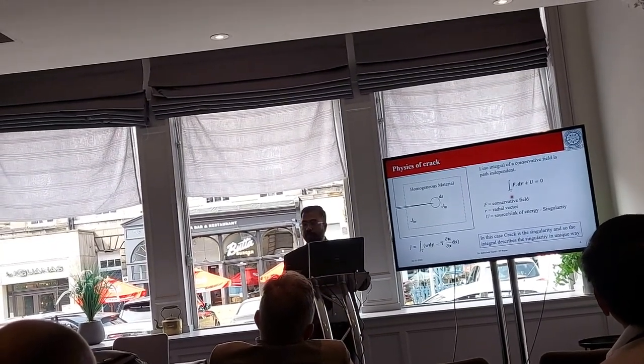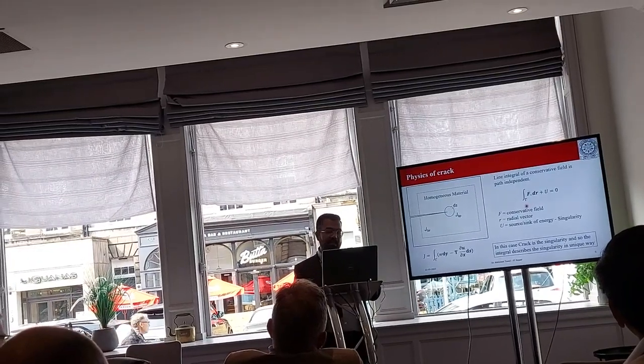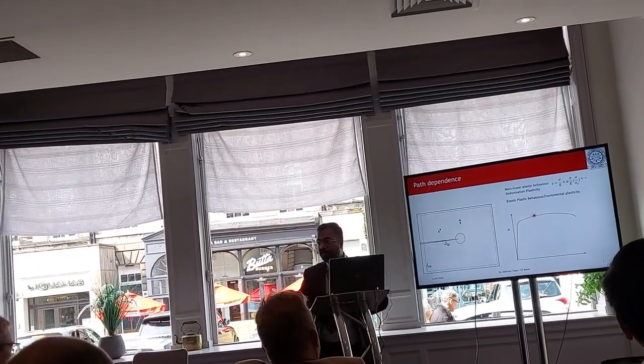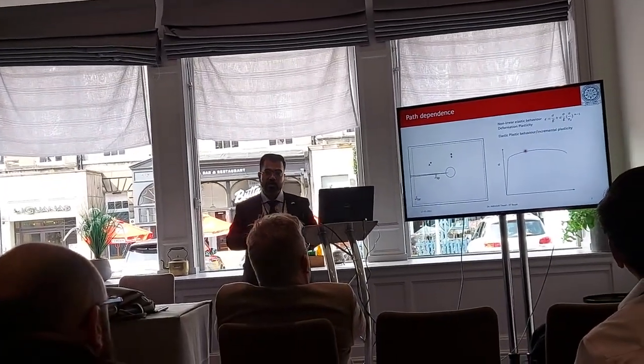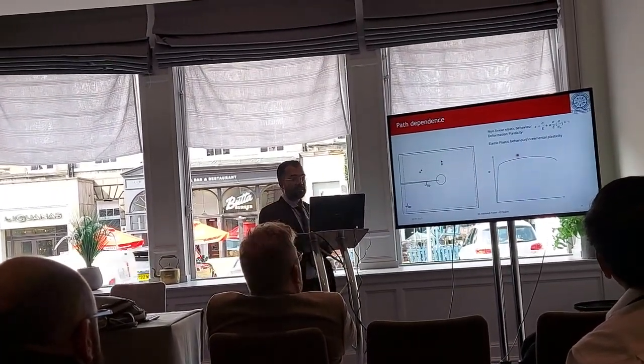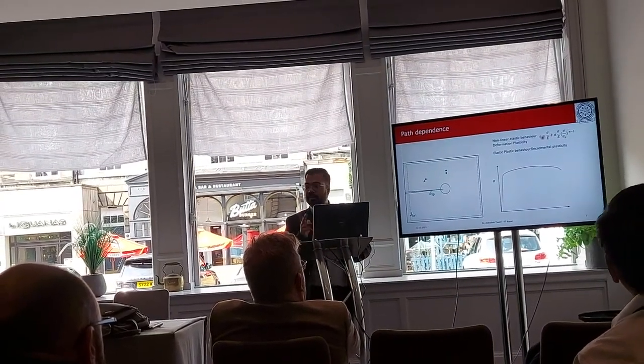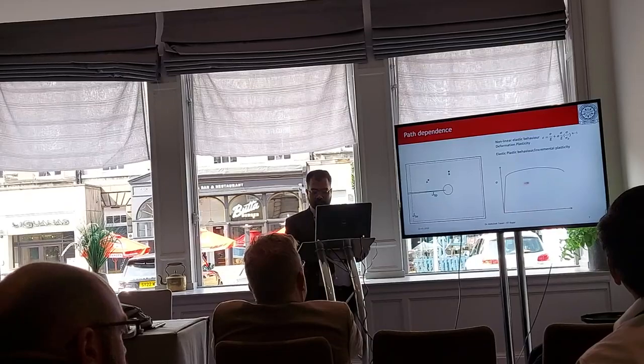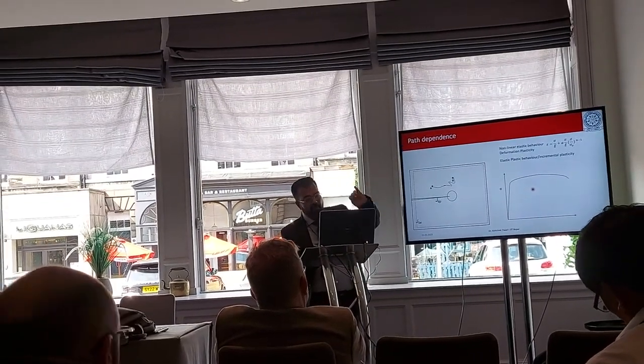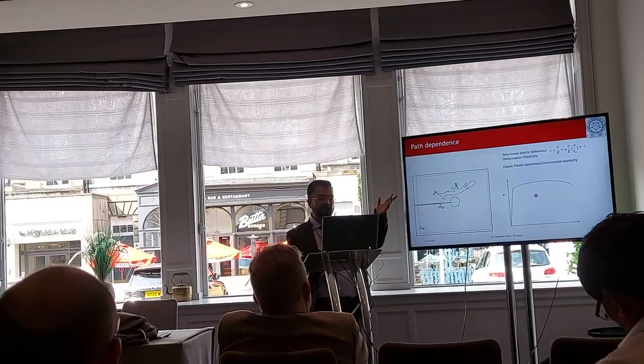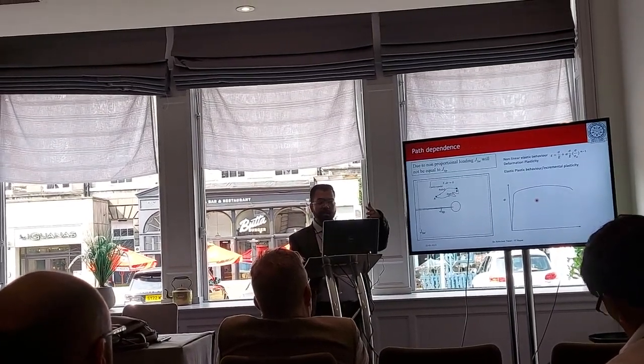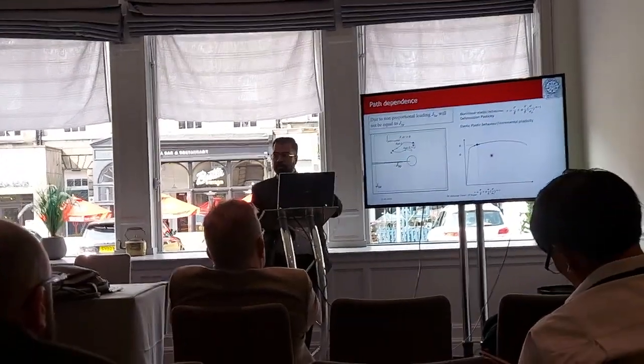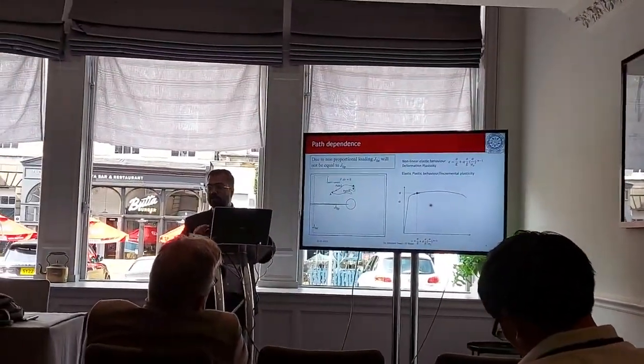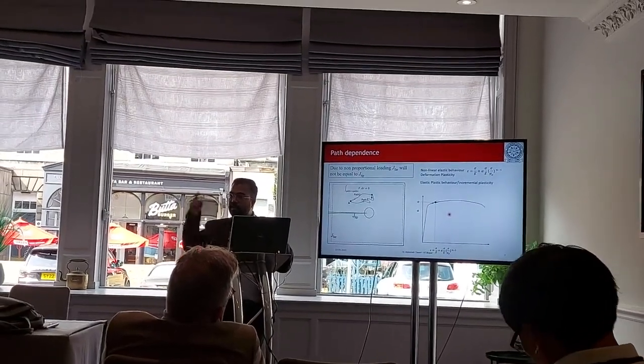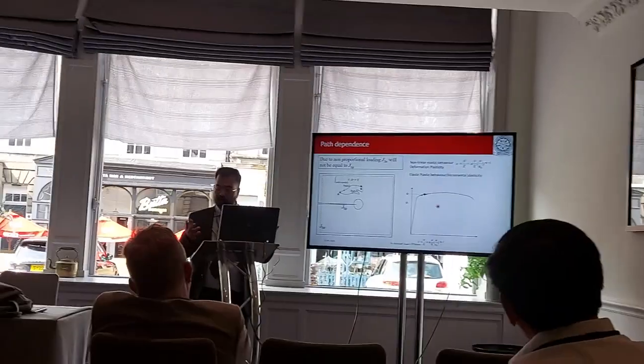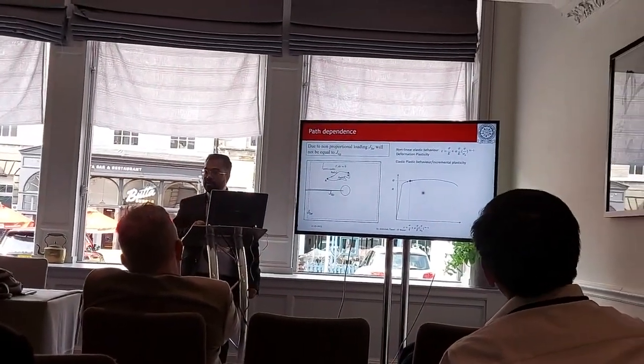There is a problem because real materials are not nonlinear elastic, they are elastic plastic, and the difference appears here. When you assume the material deforms following the Ramberg-Osgood equation, for each value of stress, you have one value of strain and vice versa. So the curve follows the same path. Here what you see is that if you go from A to B, you have some value of the integral independent of the path you take, and if you come back, it's 0. If you follow the Ramberg-Osgood equation, the point is going to move along this line of the stress strain curve. Whether you are loading it or unloading it doesn't matter. So it doesn't feel unloading. That's not a real material, that's an assumed nonlinear elastic material.